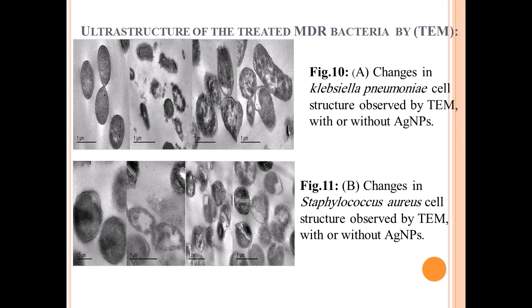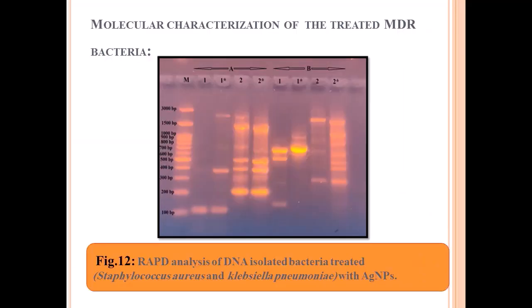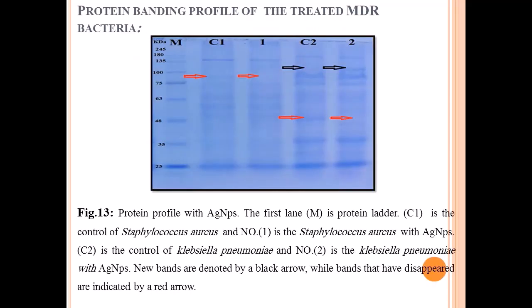Ultrastructure of the treated multidrug resistant bacteria by TEM. Figure 10a. Changes in Klebsiella pneumoniae cell structure observed by TEM with or without silver nanoparticles. Figure 11b. Changes in Staphylococcus aureus cell structure observed by TEM with or without silver nanoparticles. Molecular characterization of the treated multidrug resistant bacteria by RAPD analysis of DNA. Isolated bacteria, Staphylococcus aureus and Klebsiella pneumoniae, treated with silver nanoparticles, showed present or absent bands.